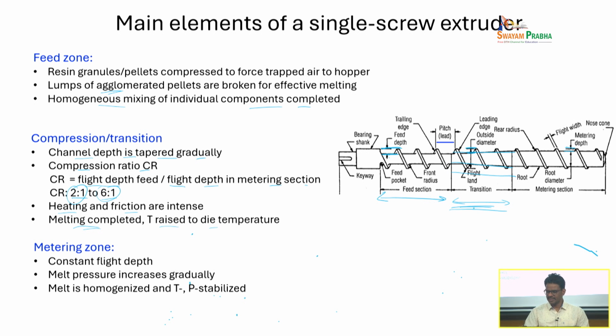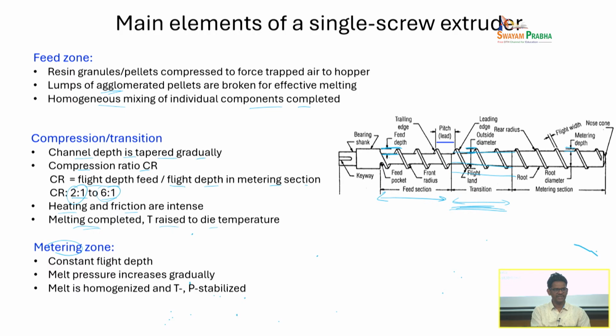So typically in the middle section, the melting is completed and T is raised to the die temperature. In this particular zone, the temperature is gradually increasing, the pressure is also gradually increasing. But then you also want a section where the temperature and pressure become a little stable, so that when the material goes through the die, it has a constant temperature and constant pressure, and that's what happens in the metering zone. The purpose of having the metering zone is to stabilize the temperature and pressure that is needed, and that's why here the depth is constant. Here the diameter of the screw and the barrel is constant. So the melt is homogenized and temperature and pressure are stabilized, so now it is ready to get extruded, right?